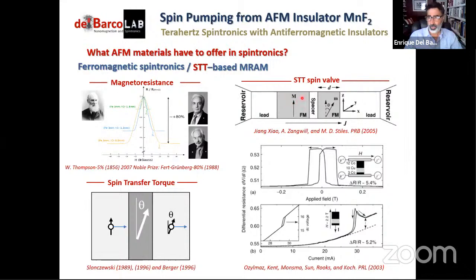That magnetic polarization is transferred to the free layer, and the spin transfer torque in the free layer generates dynamics in the free layer, and actually can even reverse the magnetization direction. And this is basically the principle of operation of a spin valve, right?